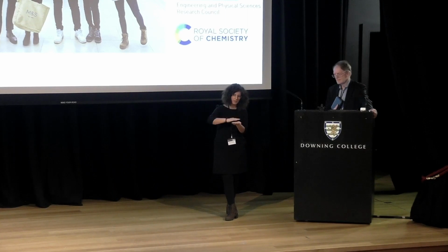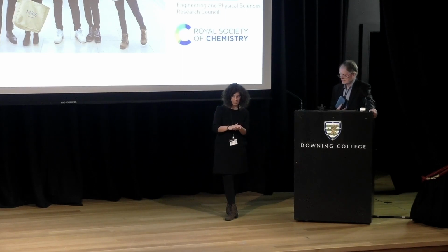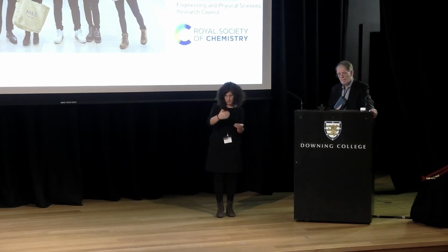The light we use to grow the nanoparticles in 3 dimensions. So we can use light, and we can use visible light to achieve that. But to grow them, to actually control where it goes in the nanostructure by layer addition, you basically do it by sequential addition of polymers. So you add polymer X, and then you add polymer Y, and so you know exactly where these are. Yes, that's done with light.